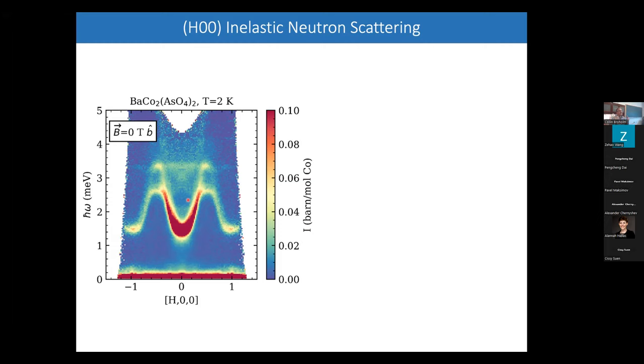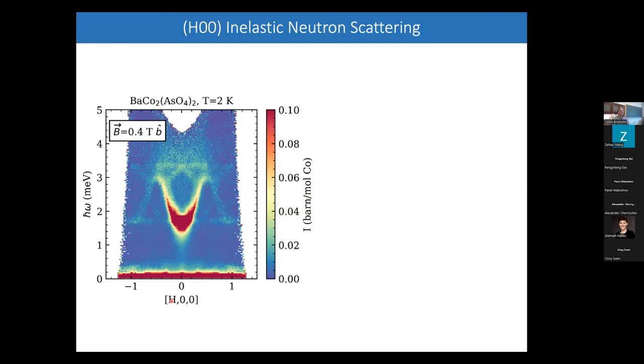Now I'm going to apply a magnetic field along what we call the B direction. So that would be perpendicular to the momentum direction because that's perpendicular to A star. And I go to 0.4 Tesla. That brings me into the commensurate state. There's some kind of changes. I've moved the spectrum up a little bit. Then we go to 0.75, which is now beyond the ordered phase.